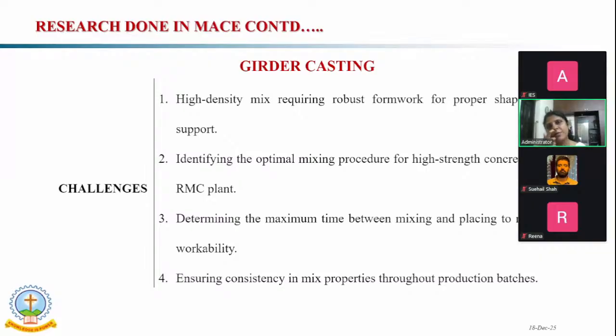Before that, in the laboratory itself, we found out the retention time we would get with the UHPC mix. We found that we get around 1.5 to 2 hours of retention period after the addition of water in the case of UHPC. To get that 6-meter UHPC girder, I think we completed it by considering 3 production batches.